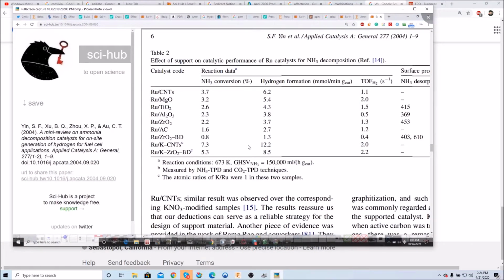So ruthenium is the most active catalyst by far. Before we start discussing catalysts, I want to just state that there's a plethora of catalysts that are considered, just a wide range of catalysts. What they all have in common is they have low rates of reaction. They have low reactivity until they reach high temperatures. With ruthenium, you get much higher conversion rates, much higher reactivity at lower temperatures. That's the main difference. All these catalysts can decompose ammonia at high temperatures above 700 degrees Celsius.